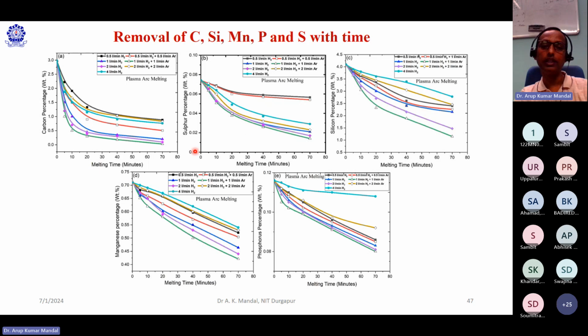After that, you can see when the exposure time gradually increases, as the liquid metal surface is superheated and the major impurities like the carbon are removed, then the removal of the sulfur happens, because sulfur is a surface active element. When the impurities at the surface are removed, then the sulfur will try to come to the upper surface as a surface active element. Therefore, you can see that drastically the sulfur is removed. The silicon pattern initially slightly decreases, after that it increases. But for two other impurities, manganese and phosphorus, we observe very little removal.